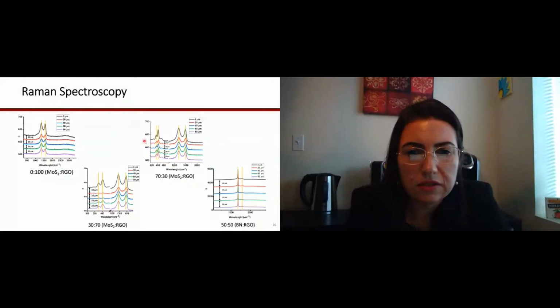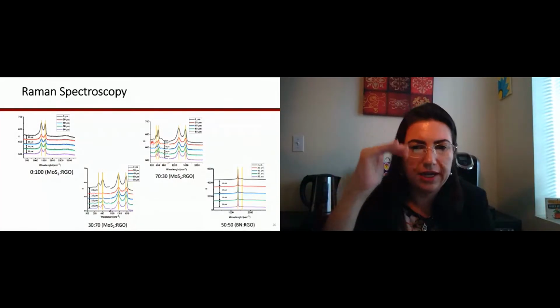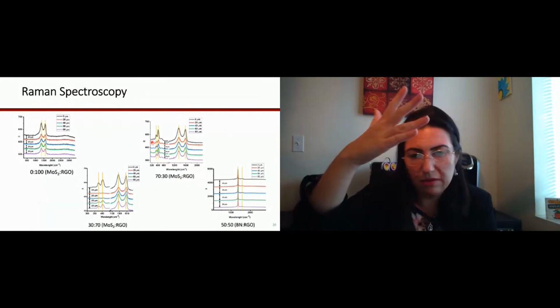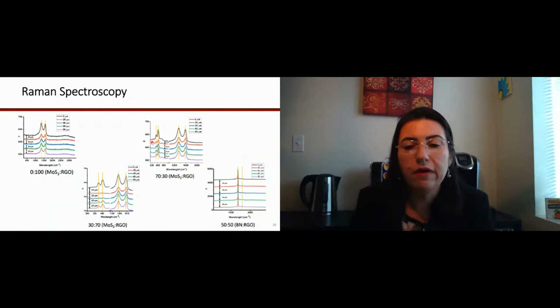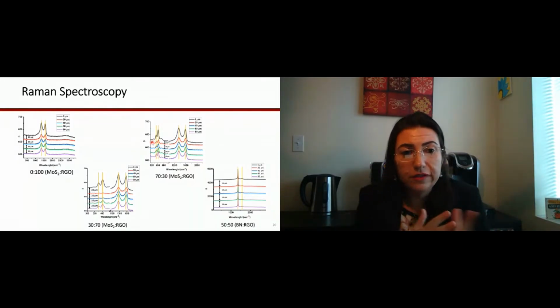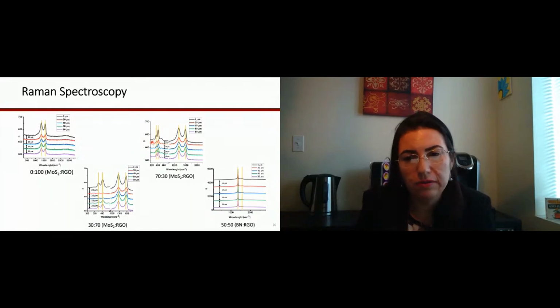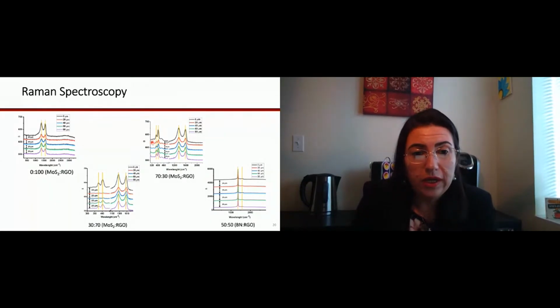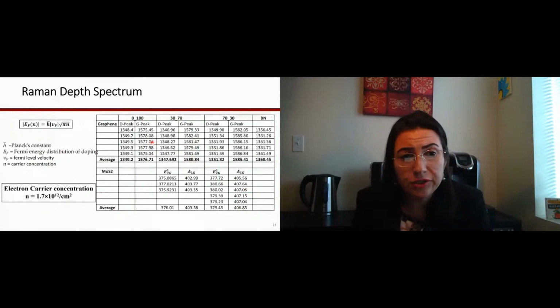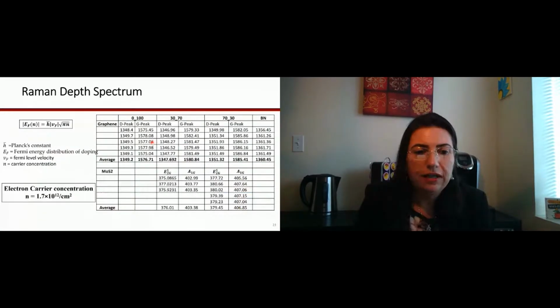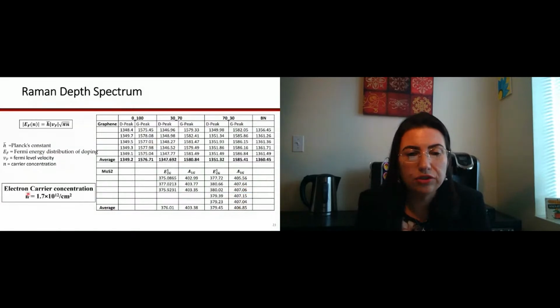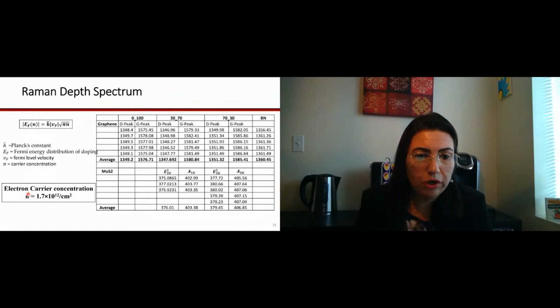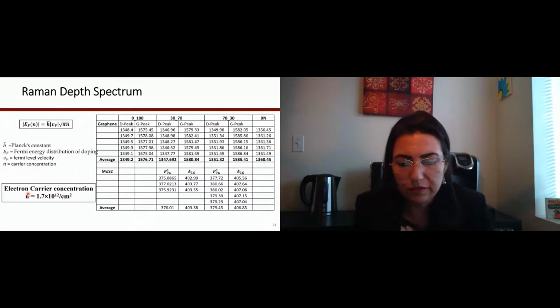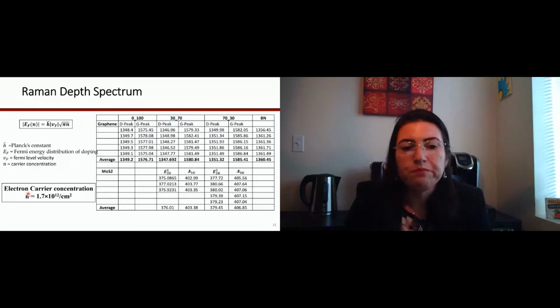And those scans are done 20 microns apart. So every line you see is from the top of the sample going 20 microns in depth as we're scanning those samples. So as you can see, all of this shows all the characteristics for all the material that we have. We can obtain the carrier concentration. This value means how many free electrons we have to be able to flow on this device. And this was really important for the electronic applications of our devices that we wanted.